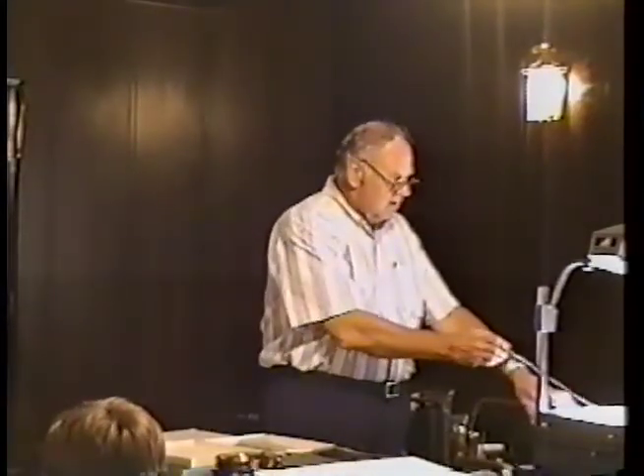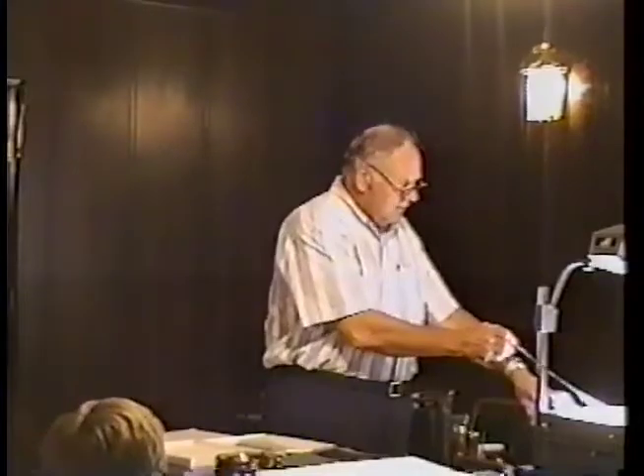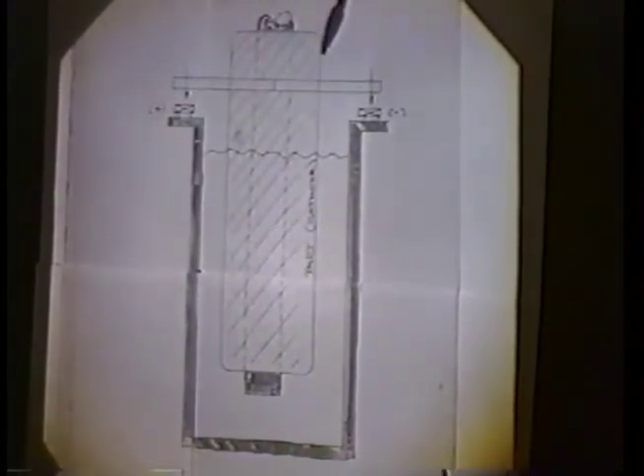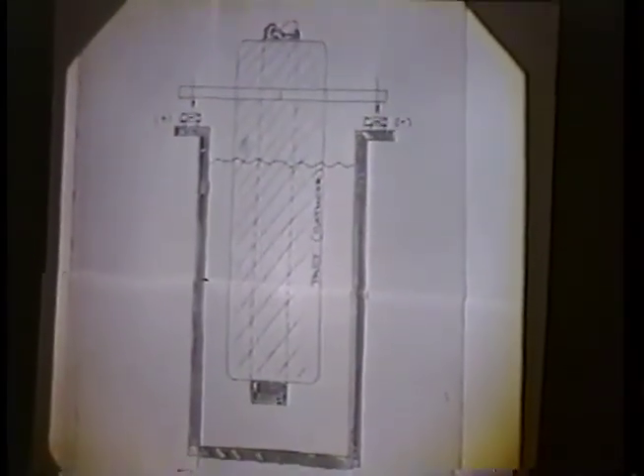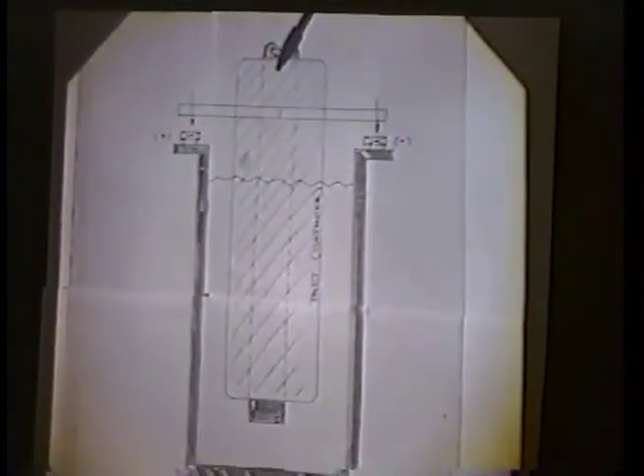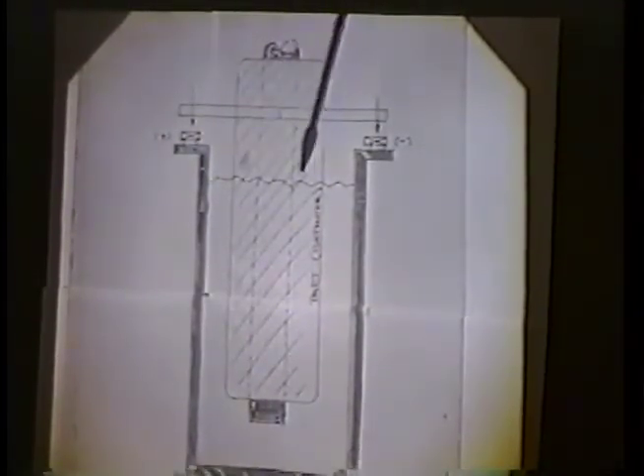And additionally, the liner itself must be fixtured to what we call a rack, which conducts the electric current. The part itself, the liner in this case, becomes what is known as the cathode. And inserted down through the center of the liner is a tube that has very definite spacing. It's big enough to allow at least a ½ inch of spacing down to as much as a ¼ inch of spacing between itself and the liner surface that you're plating.